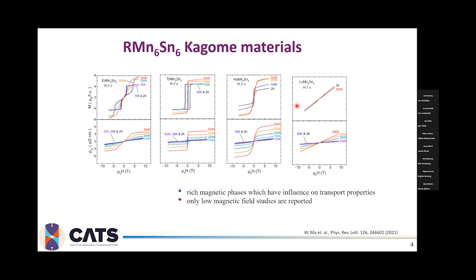On the other hand, the lutetium, which is a non-magnetic material, shows a very linear Hall effect. So what was interesting for us in that case is that all those rich magnetic phase diagrams strongly influence the transport properties and might also influence the topological properties of those materials. However, at least to my knowledge, they were studied very intensively in the low field, but there are not many reports about this family of materials in the high field.